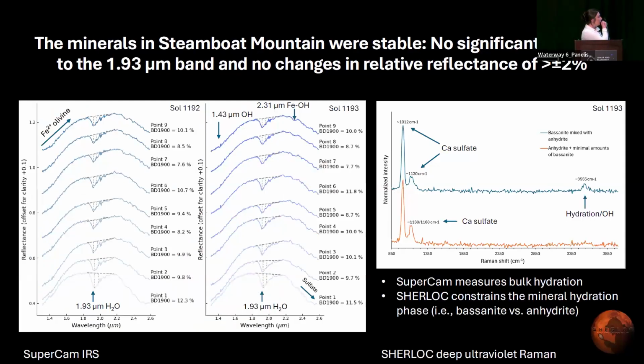So here's the actual band depth calculations. And as you can see, there's only 2 sols that I'm showing here. That's really because the rover had some ARM activities in between the SuperCam activities that resulted in the IRS field of view shifting just a bit. Of course, it can also be indicative of thermal expansion of the rover mass that SuperCam is sitting on. But if you look from point 9 here and point 9 there, they look relatively the same.